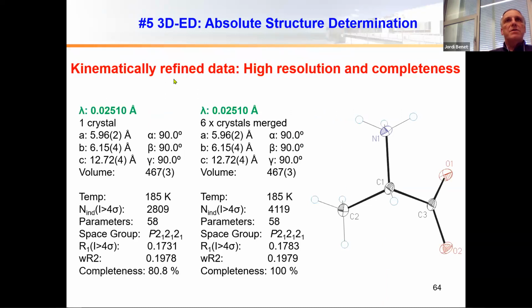So these are, let's say, the so-called canonical refinements of the data, and you can see from alanine, from one crystal, we could solve the structure with a good parameter to reflections ratio and an R1 value of 17%, which is still okay. From one crystal, this was having only a completeness of 80%. After merging 6 crystals, we got a completeness of 100%.